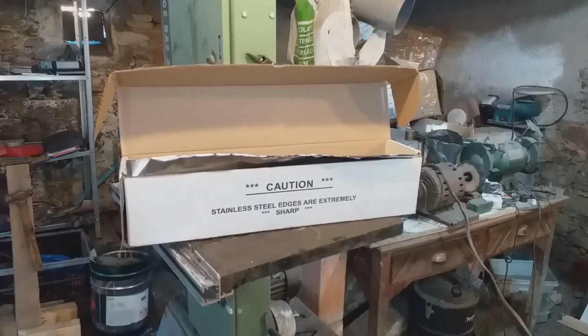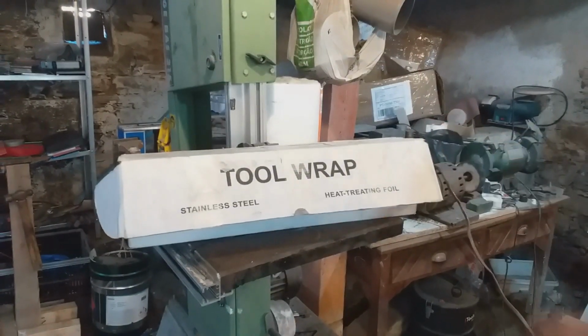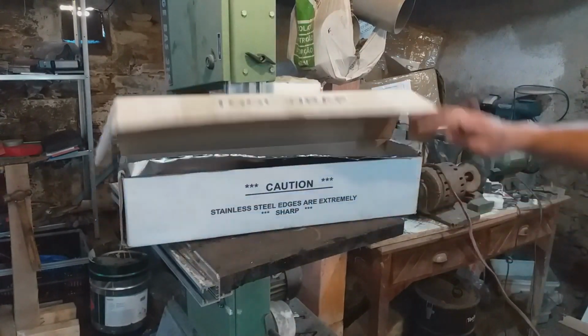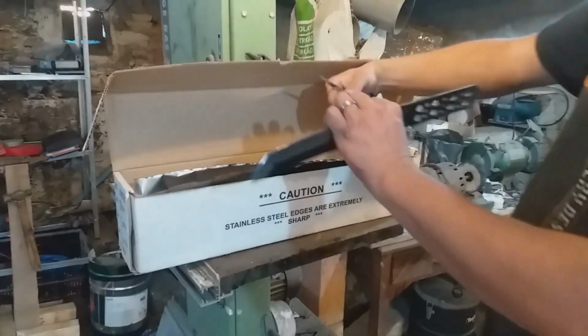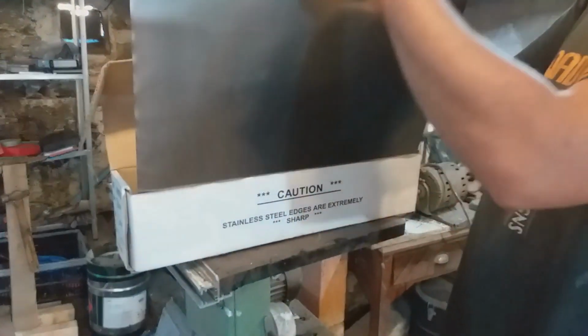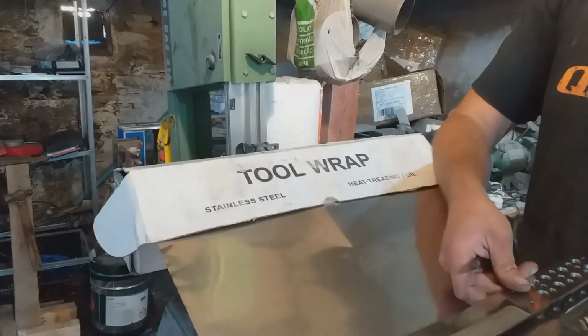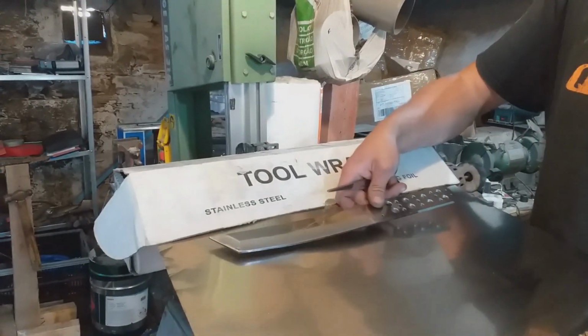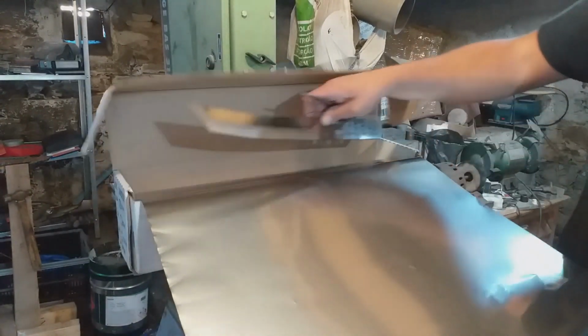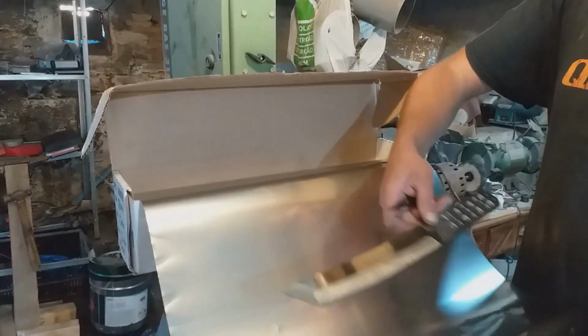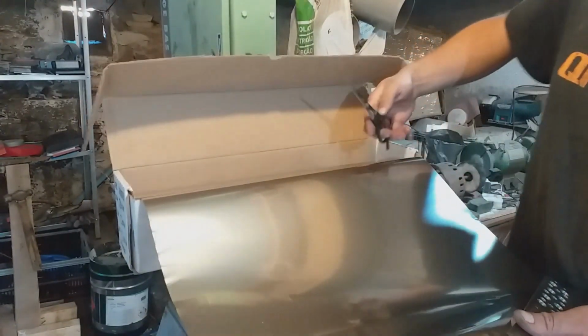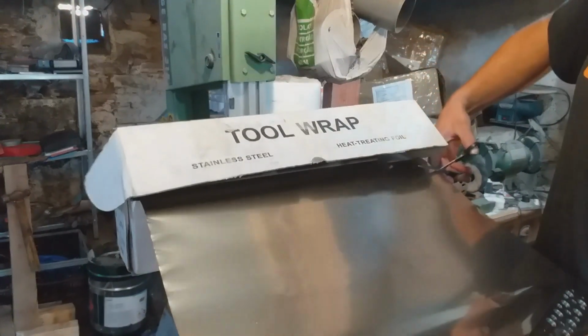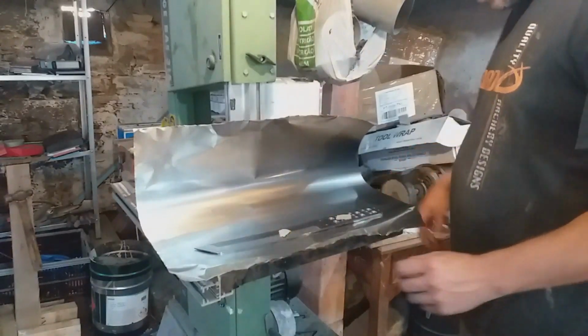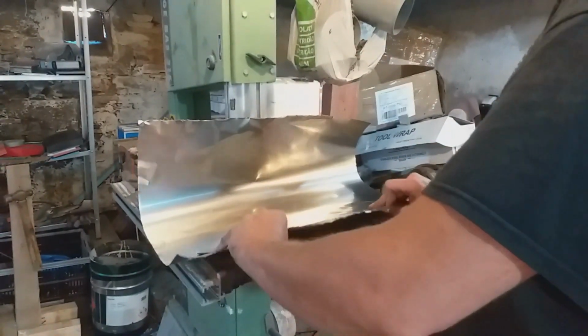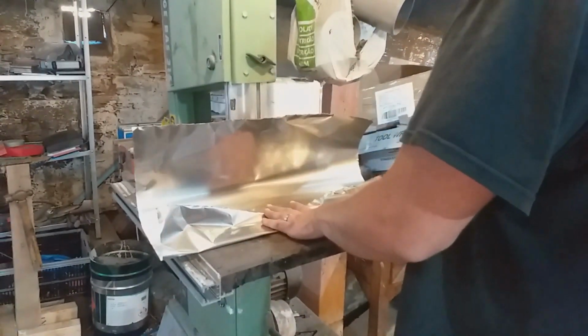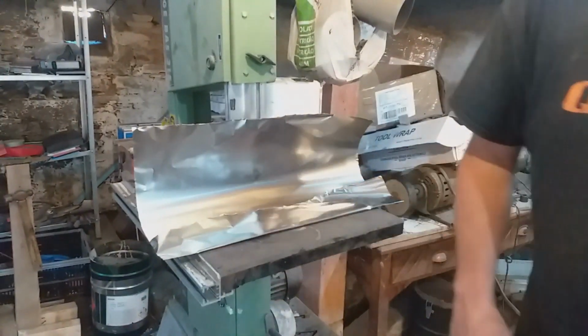Because this is a stainless steel knife, the heat treatment process is very complex. The blade itself needs to be wrapped into a protective atmosphere where the stainless tool wrap comes into play. This stainless steel wrap will withstand the heat of being in the furnace up at 1050 degrees centigrade, so that the carbides inside the metal don't actually get burned out. So it's almost like a sacrificial environment that keeps the blade away from oxygen while it's up at temperature. Without this, the blade would be left blackened and burned.